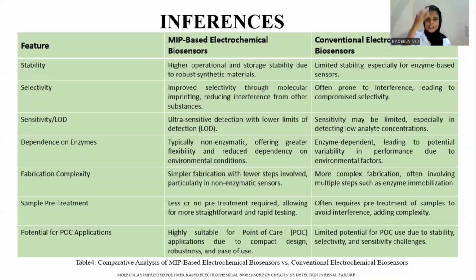And then the comparison of the MIP-based electrochemical sensor and the conventional electrochemical biosensor. From the table itself, we conclude that the MIP-based electrochemical biosensor offers high operational and storage stability, improved selectivity, ultra-sensitive detection with lower limit of detection, and is typically non-enzymatic. So the enzyme storage stability issues do not occur here. It also has simple fabrication with fewer steps, little or no pre-treatment required, allowing more straightforward and rapid testing, and is highly suitable for point of care application due to compact design, robustness, and ease of use.